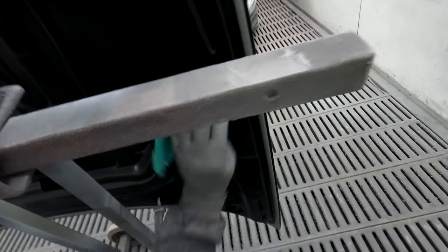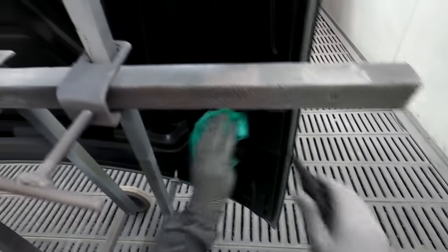I first came here. What I was using when I first came here, I was using fast hardener in it because I came from Glasurit, whereas you could use fast hardener in it. So that's part of the reason I was getting grit in it, I think now. But yeah, coming to this Standox stuff, you really do have to use the slow hardener in it. And yeah, just really observe those flash off times.